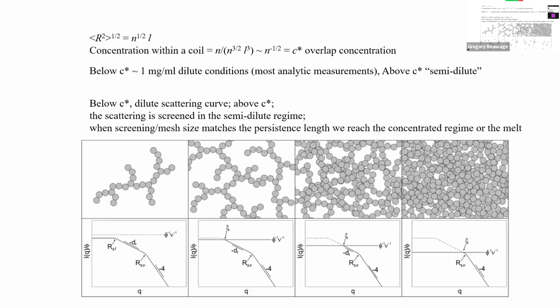Yeah. So in order to do this, you need to have different masses, and then compare, and then plot the density versus the mass. And then it would have a power law. So you do log density, log mass, do a power law slope, and the slope would be 1 minus 3 by df. The df would tell you the density scaling with mass, right? So it's not telling you anything about exactly what the thing is. You can tell it's not a rod. You can tell it's not a 3D object.